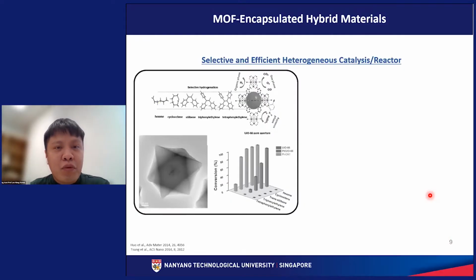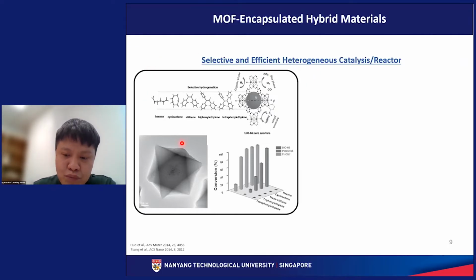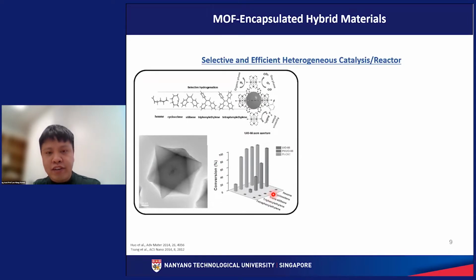So in this section, I will basically focus on MOF encapsulated hybrid materials and their use as a selective and efficient heterogeneous catalyst or reactant. MOF are frequently used with catalytic materials, like metals, to enhance the selectivity of this catalyst towards certain reactions. So for instance, by making use of the pore aperture, we are able to selectively filter out big molecules while only letting small reactants enter the MOF structure and access the embedded catalyst. So this leads to very high selectivity towards certain target reactants.